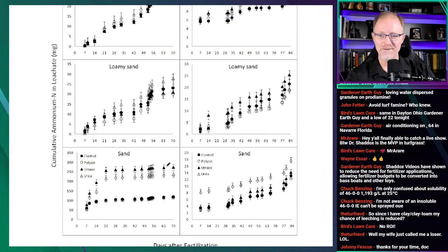So let me explain what's going on here. She's talking about the ammonium leaching from the loamy sand. And she said in the first year, 2008, more ammonium was leached from the urea. Which, you could argue one way or the other. You could say the urea converted more of the ammonium, or less of the ammonium was retained in the soil. But what you can't argue is that one year urea resulted in the most ammonium leaching, and then the next year it was the UMaxx that resulted in the most ammonium leaching. So there wasn't any consistency with the UMaxx, the product we're paying double for.